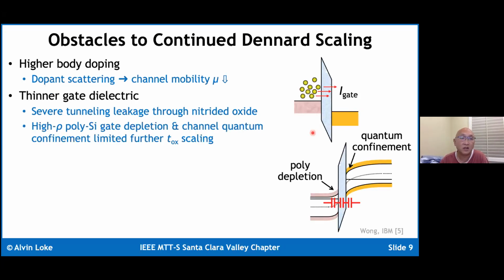Okay. We also have, as we thin down the dielectric, we run into an issue where we've got the finite conductivity, I'm sorry, of the polysilicon leads to poly depletion, which means that the charge on the gate is not going to be infinitesimally close to the gate oxide interface on the gate side. And so the charge centroid on the gate gets pushed out away from the interface. Furthermore, the increased doping concentration causes these quantum confinement effects.